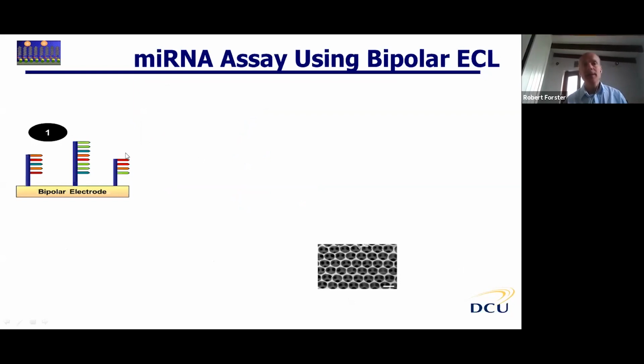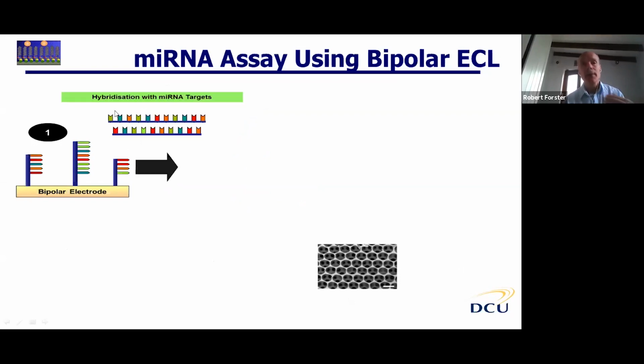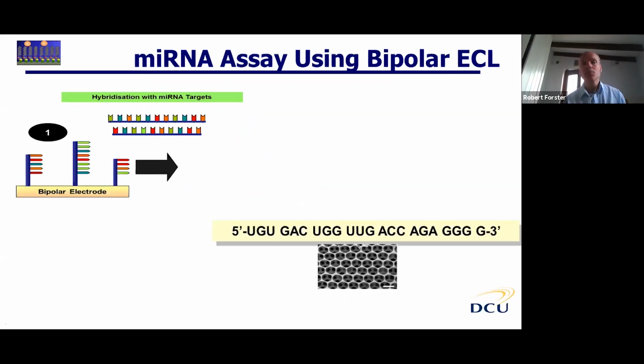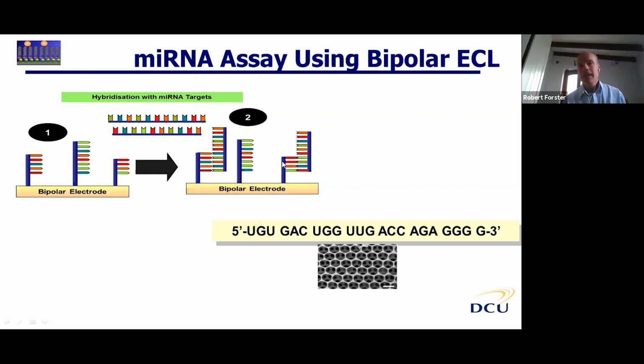So what we can do then is build classical DNA sandwich assays on that surface. We can put capture strands down on the surface, bring in our targets. If the target is complementary to one of our capture strands, we can see binding of that target to the surface. Then we can bring in a probe strand that has our luminophore, our ECL active luminophore, on the surface.